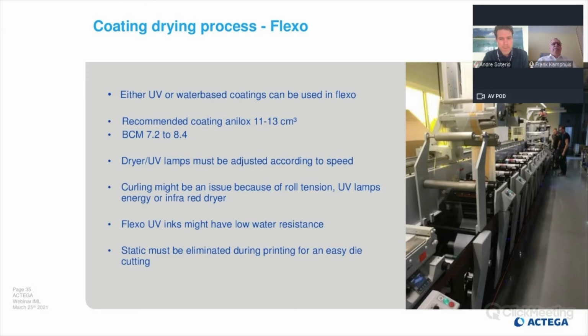If you are working in a flexo process, you can use both UV coating or water-based coating. So again, the recommendation for the BCM is roughly 7.2 to 8.4. And it's important that you adjust your dryer. That means, for example, for UV processing, the energy of a UV drying lamp is very intensive. So if it's too much, you could get problems with curling, or if an IR dryer is too high with water-based coating, there could also be some problems.